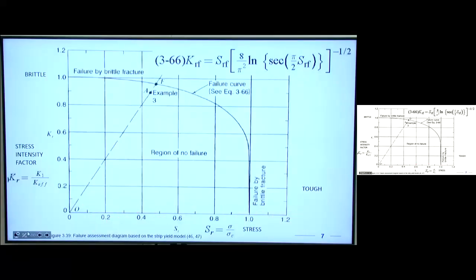And so what we can do is then inside the line, we have no failure. We do not expect either failure. If we're outside the line and we're kind of close to this side, then we would expect a plastic collapse through the cross-section of the material. And if we're closer to this side, we'd expect a brittle fracture. And if we're in the middle, it really is a toss-up between the two. It's probably a combined failure mode. But this chart, this failure assessment diagram, allows us to check for both.